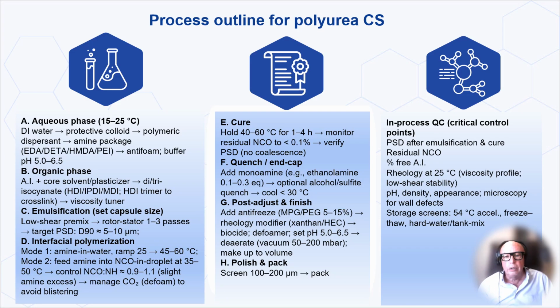Process outline for polyureas. Now let's look at the actual process for making polyurea capsules and the critical control points. The process follows a logical sequence. Build your aqueous phase with dispersants and amines at pH 5 to 6.5. Prepare the organic phase with active plus isocyanates, then emulsification.